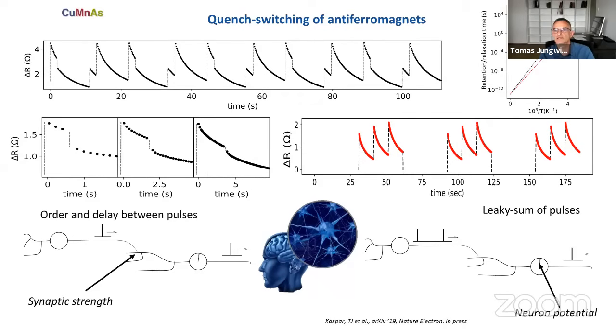And of course, if we heat the system up, we will accelerate the relaxation. And this is, by the way, also the mechanism which allows us to quickly erase the state and write a lower resistivity state, because we highly accelerate the relaxation by delivering the second pulse, and then we just write the lower resistivity state.